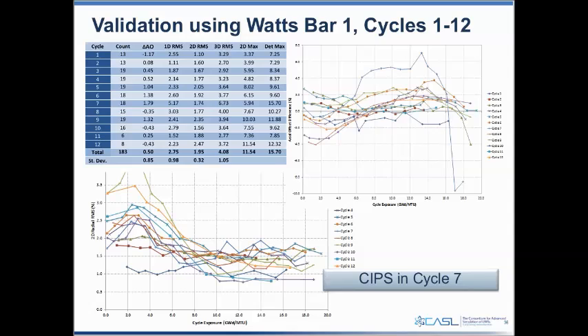But in the top right, we're looking at the axial offset. As Jeff mentioned, the axial offset is the ratio of the top to bottom power distribution. You can see that there was one cycle that was really unusual, and that was cycle 7. Cycle 7 in Watts Bar 1 experienced some significant CRUD-Induced Power Shifts (CIPS). And as you can see, our simulation of that, since it didn't include any MAMBA calculations, was pretty significantly off, despite the fact that on the other cycles it was pretty good.